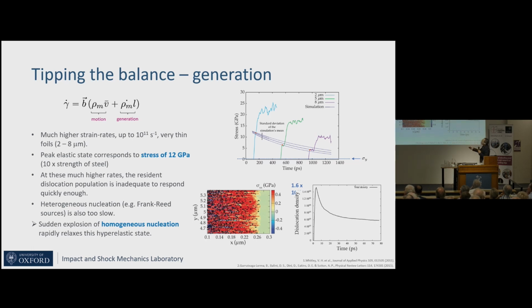And let's see in this equation, where before it was essentially governed by the first term, motion, what happens if it's governed by the second term? And Benyat, this talented student, performed a simulation where he threw away all the dislocations. He said, let's pretend it's pure. And he was able to replicate and match the experimental data that we've got, principally the yield points here, by allowing an eruption.